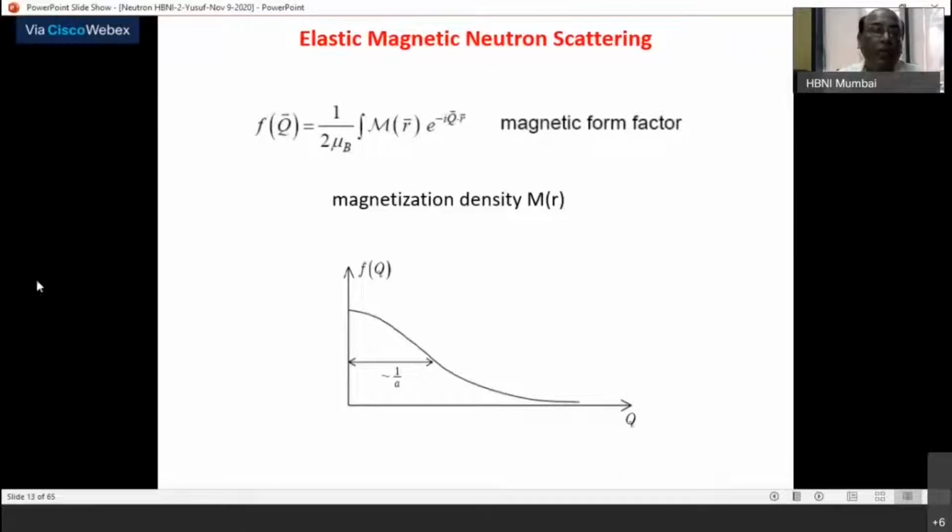So when you do this neutron diffraction for magnetic material, when you look for magnetic Bragg peaks, you have to always design your instrument in such a way that it is able to measure from relatively lower 2 theta, and the instrumental resolution, the spatial resolution, is better over this lower 2 theta range, because your intensity is anyway going to fall after a certain q, after a certain 4 pi sin theta per lambda, after a certain 2 theta scattering angle.